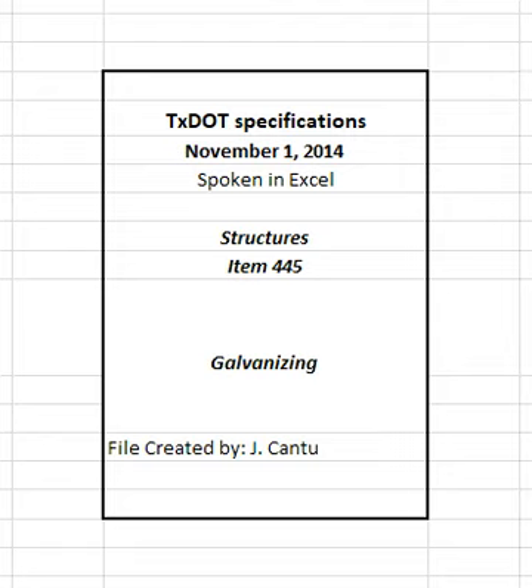3.4.3.2 Red rust. Red rust on galvanized items indicates uncoated areas. See Section 445.3.4.1, Coverage, for acceptance criteria. 3.4.3.3 Alligator cracking or spider webbing. The composition of the base metal may cause dark lines resembling alligator skin. See Section 445.3.4.2, Adhesion, to determine whether the coating is acceptable. 3.4.3.4 Dull gray coating. The composition of the base metal can cause a dull gray color. See Section 445.3.4.2, Adhesion, to determine whether the coating is acceptable.